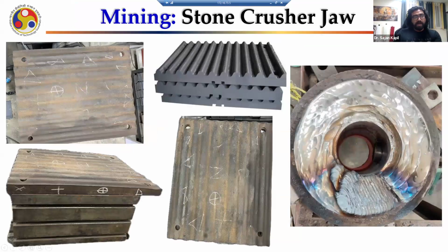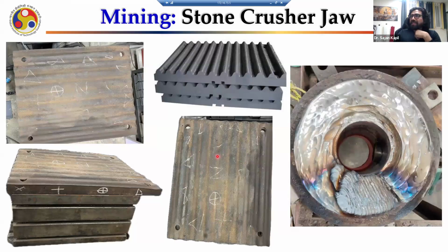We have got a case from the mining industry. It's a huge die, around 600 kg, I believe. And a small portion of that got worn out, this portion. It's around 30 kg only. We scanned it already. We found a suitable material. It's a high manganese alloy. And that's where I need my metallurgist friend to help me in identifying which material I can deposit onto that.